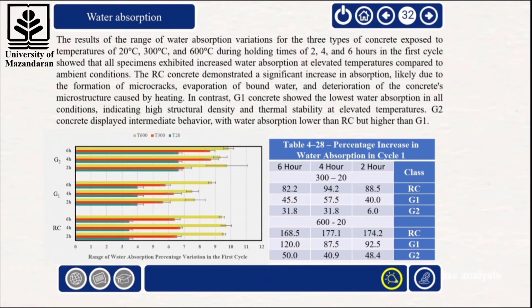RC showed the greatest increase, likely due to the formation of microcracks, evaporation of bound water, and microstructural degradation under thermal exposure. In contrast, G1 exhibited the lowest water absorption under all conditions, indicating its dense structure and high thermal stability. G2 displayed intermediate behavior, with water absorption lower than RC but higher than G1.